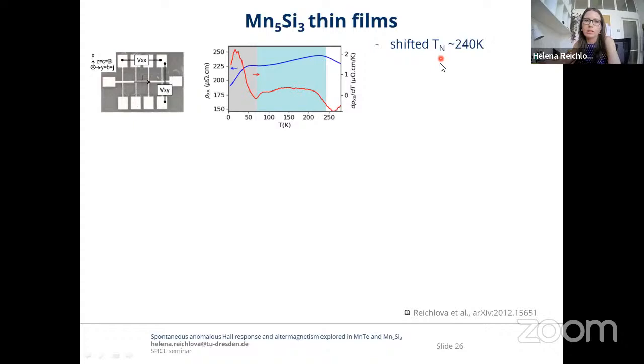We fabricated bars where we measured the longitudinal and transversal voltage. And here I show the longitudinal resistivity, which has a similar value as the bulk, and similar to bulk, it shows two bumps or two moments which indicate the phase transitions. The first, low temperature phase transition seems to be not strongly changed. However, the second phase transition to the paramagnetic state seems to be shifted up to approximately 240 Kelvin.